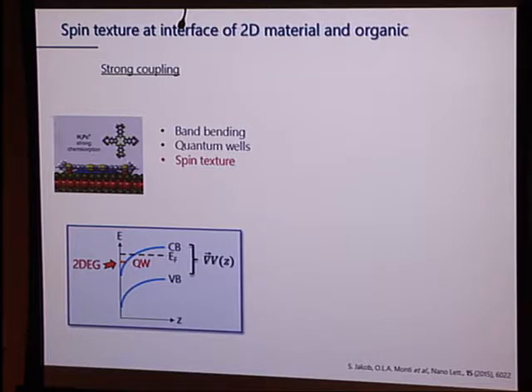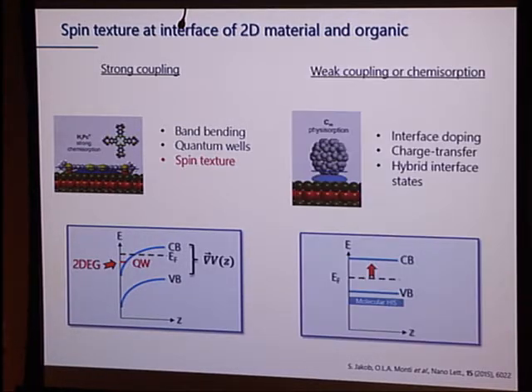And because we interact so strongly between the molecule and the surface, there is a lot of charge displacement that happens. That is what creates the electric field. That leads to strong band bending. It is that band bending that leads to the potential gradient. The existence, actually, of a two-dimensional electron gas, if you really want to dig into this, in a quantum well. But it's this potential gradient that, together with the momentum in the crystal, generates the Rashba splitting.